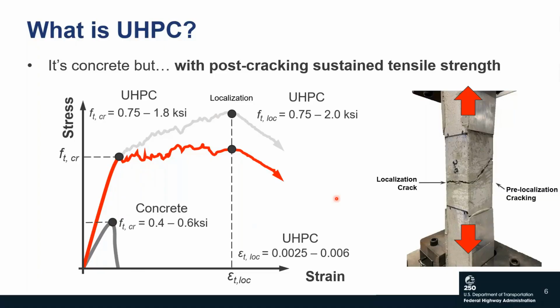So multiple cracks are forming, they're being bridged by those fibers, but the cracking stress within that multiple cracking region is maintained with increasing strain or even exceeded. And that behavior continues until the fiber bridging capacity is exhausted and the fibers can no longer hold these tight cracks together. Then one of these cracks starts to open up, what we call the localized crack, and the fibers in that crack start to pull out. That phenomenon we call crack localization. And this crack localization point is a very important property in UHPC because after that, tensile capacity starts to drop with increasing deformation, and the deformation starts to localize all into that one crack that continues to open up.